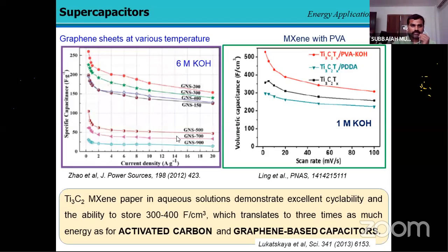They found that up to 200 degrees Celsius, they achieved more specific capacitance with the help of 6 molar KOH electrolyte. But when compared to the MXene materials, it was found to be lesser. And this is the simplest example I'm telling here. And also the MXene-based material with PVA showed a higher volumetric capacitance, which is 2 times higher than the graphene-based material with the help of 1 molar potassium hydroxide as electrolyte.